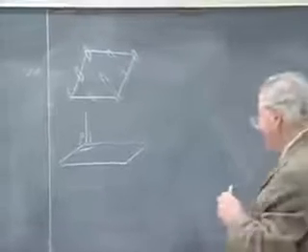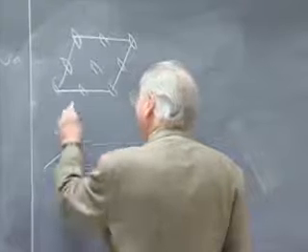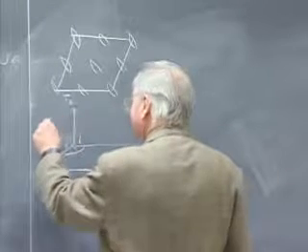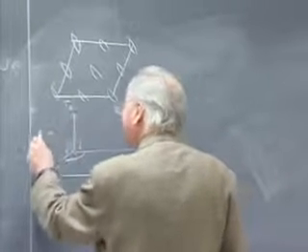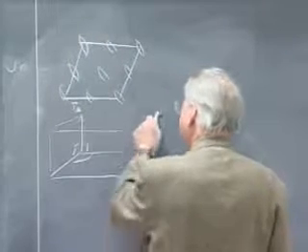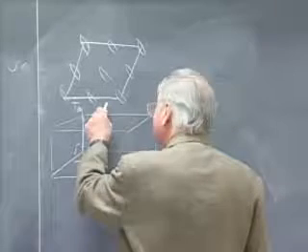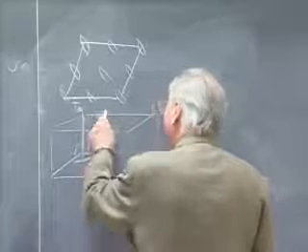The lattice is going to have two angles between axes that are exactly 90 degrees. Not approximately so, but exactly so, because only if that translation T3 is exactly normal to the base of the cell will the twofold axes in all of these nets line up exactly.